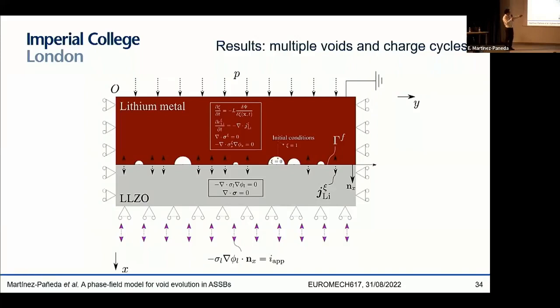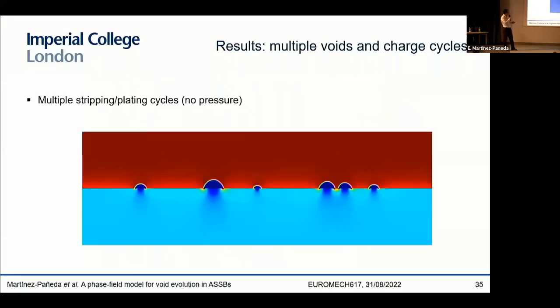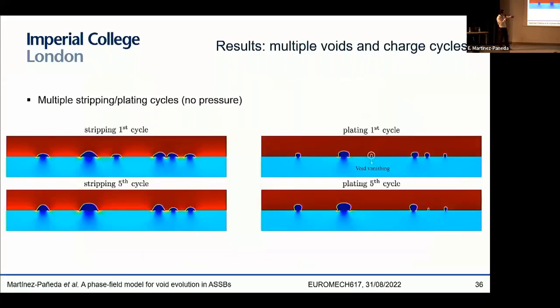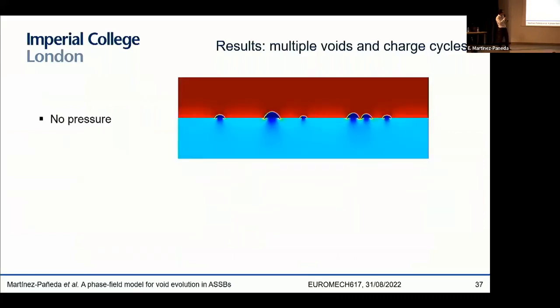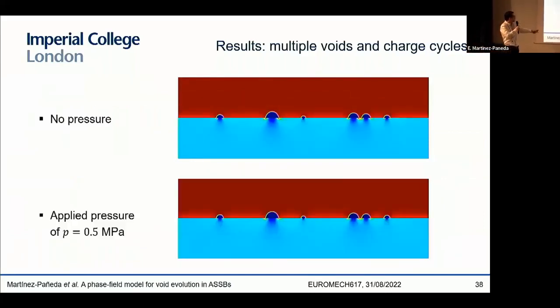So let me show you some results with a more realistic case where you have multiple voids, and you're applying a pressure or not applying a pressure. We will see both scenarios, again solving that coupled electro-chemo-mechanical problem. And you can see here, in the absence of pressure, multiple cycles of charge and discharge, and you can see how the voids grow and shrink, so to say. You can see here the evolution of the interface after multiple cycles. You can see here the influence of pressure. So you can see here what happens when you start. This is in the case of no pressure. And here you can see what happens when you apply a pressure of 0.5 megapascals.